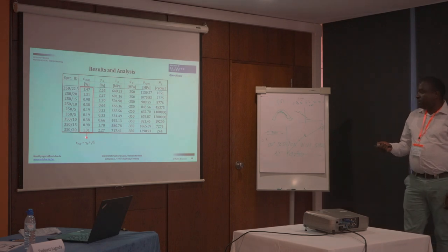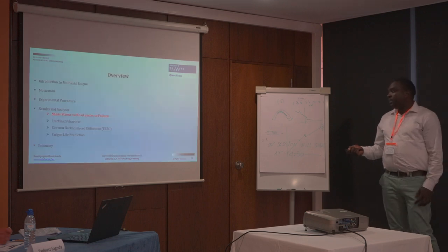This formula was used to calculate the equivalent strain amplitudes from the shear strain amplitudes. And the von Mises equation was used to calculate the equivalent stress amplitude from the shear stress amplitude and the static compressive stress.